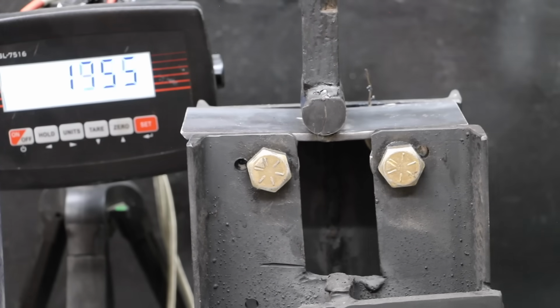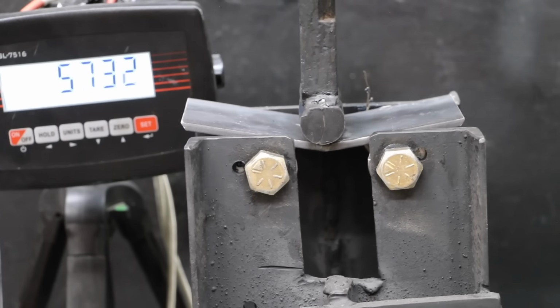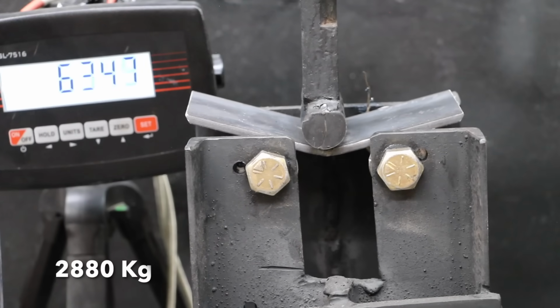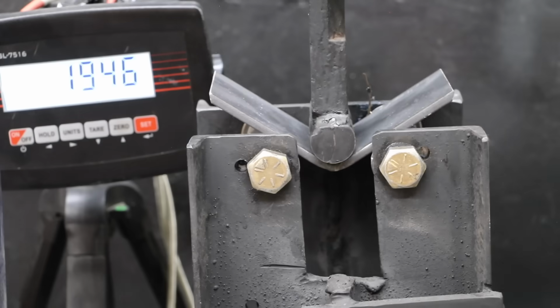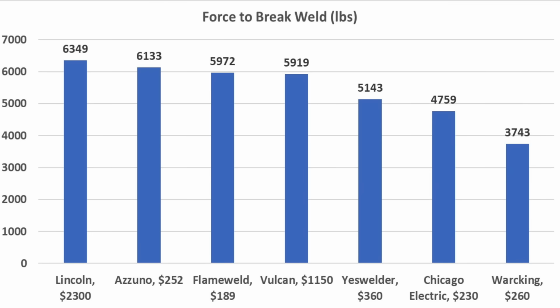And the Lincoln did indeed put together a very impressive performance, moving into first place with the strongest weld at 6,349 pounds. Very impressive. Placing a cap weld in all the test pieces would have helped, but the welding machines performed very well except for the Warcking. And the Chicago Electric was also a little below average at 4,759 pounds.